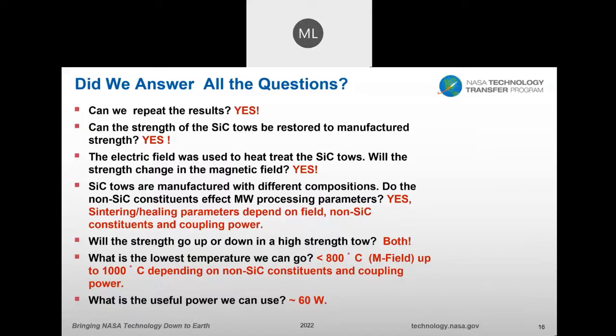Do the non-silicon carbide constituents affect the microwave processing parameter? Yes. So we saw sintering and healing parameters depend on the field, which one we use, either electric or magnetic, and non-silicon carbide constituents and coupling power. Will the strength go up or down in the high strength? It does both. What is the lowest temperature that we reached?